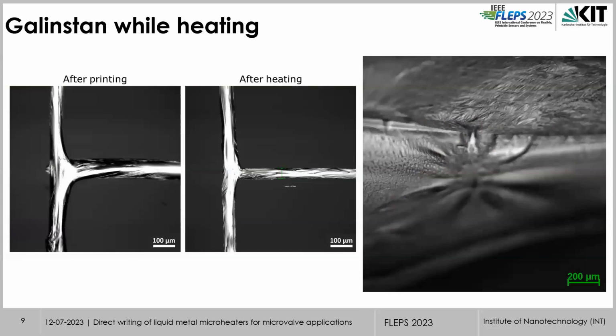But this is already known in liquid metals being used for microheaters, that we have some problems while heating. As we see here on the left, this is a freshly printed liquid metal line, and after applying some bias and heating, we see that there is some kind of shrinkage, in height as well as in width.